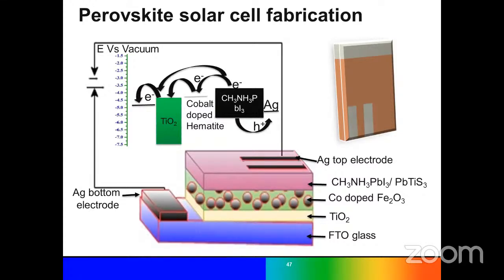In the case of the solar cells, we first checked without putting it in the water, to see how much solar cell efficiency it gives in the photoanode section. Here, in the middle is the cobalt doped hematite material. At the bottom is FTO, fluorine doped tin oxide. On top of the FTO is the buffer layer TiO2, and the upper top layer is the perovskite material. Then on top there will be the hole transport material, then the contact of Ag or silver paste.